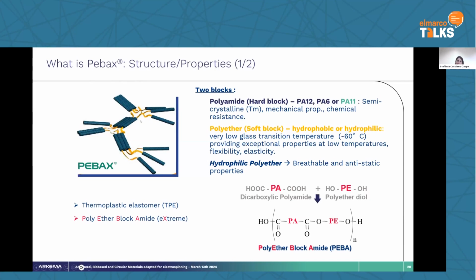And we have a soft block, which is a polyether. This polyether, with a very low glass transition temperature, makes Pebax the material of choice for winter applications, for example, for markets in which we need to ensure a very good mechanical stability over a very broad range of temperature. We can have some elasticity due to this soft block as well. And we can play with the nature of the polyether, which can be either hydrophobic or hydrophilic. When you have hydrophilic polyether in our composition, our Pebax can be used as permanent antistatic additives, as well as breathable solutions, for example, for breathable membranes, for apparel, or for house wrap membranes. So we can also have these breathable grades.